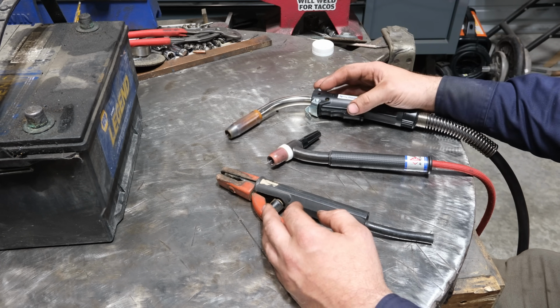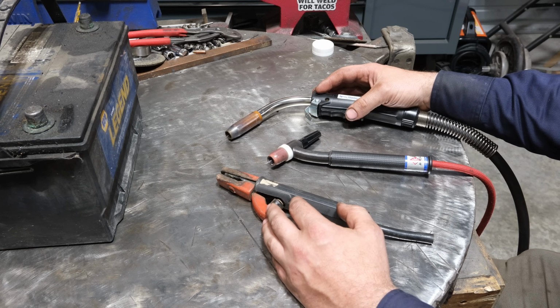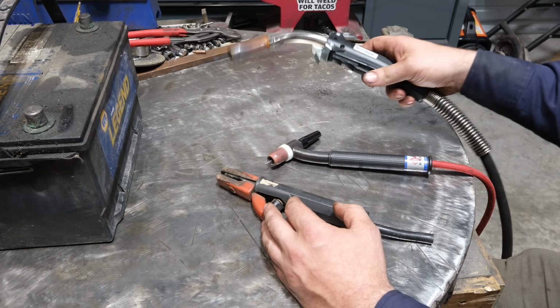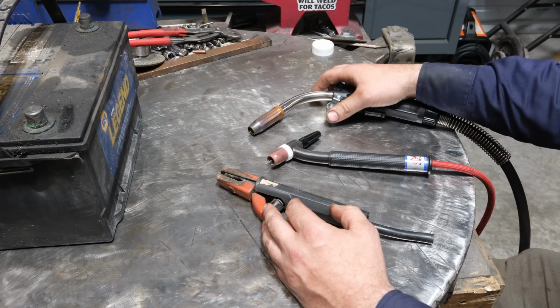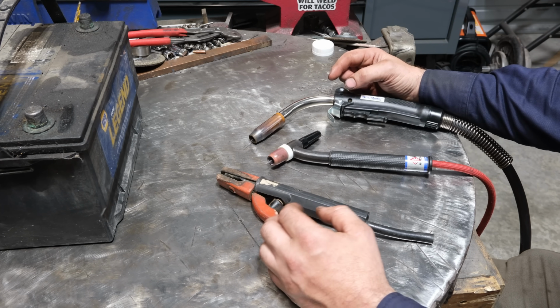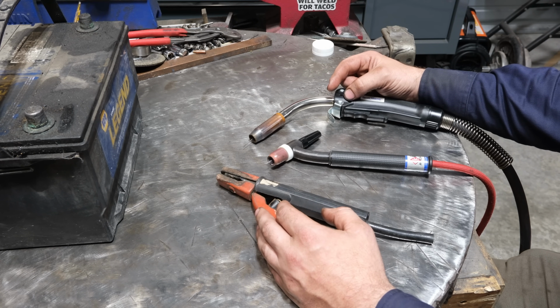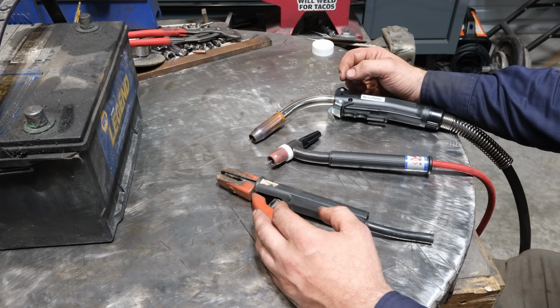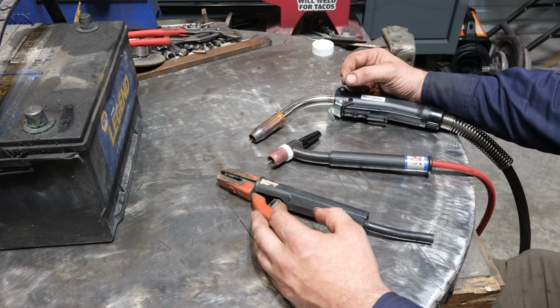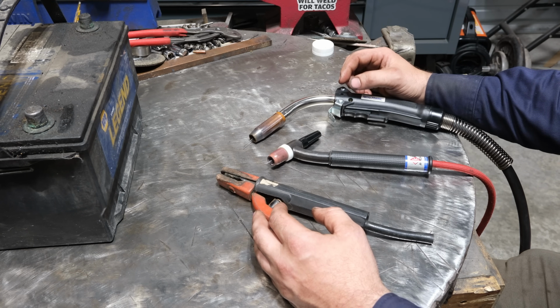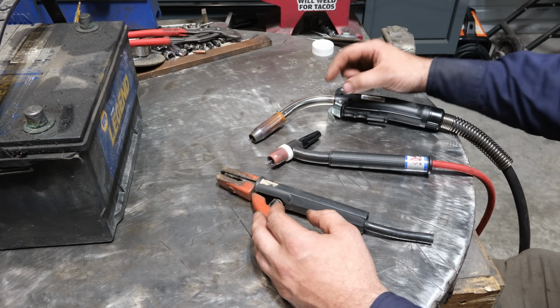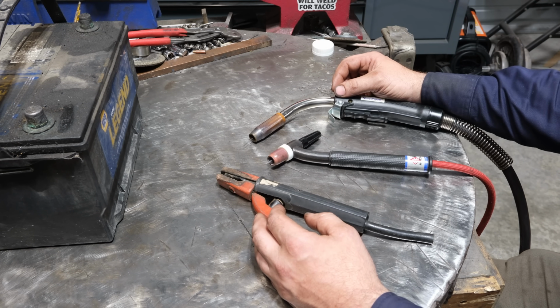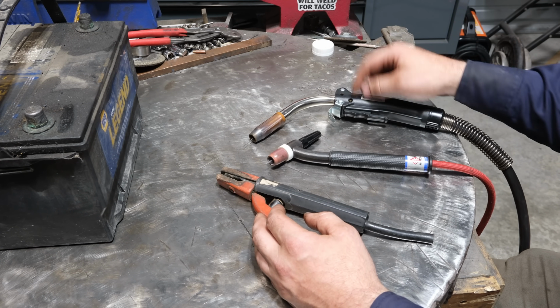Now, if you want to do some fun experiments on your own to see some of this, take your standard MIG process, which is done DCEP, and switch it to DCEN and try and run a weld. You will be successful in running a weld. It's going to sound a lot different, and the finished result is going to be a high ropey bead with virtually no penetration. No matter what your settings are, it's going to want to stack metal on top of itself rather than wetting out. So that's pretty fun.